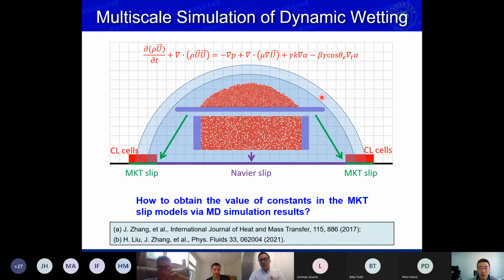To briefly summarize this method, this figure shows our strategy. In the momentum equation, we add a source term to account for the equilibrium effect for the contact angle. For the slip, we have Navier slip in the center and the MKT slip at the contact line. We don't need any dynamic contact angle model, and the shape is automatically calculated based on the volume fraction. So now the remaining problem is how to determine the parameters in the MKT model and the slip length in the Navier slip length model.